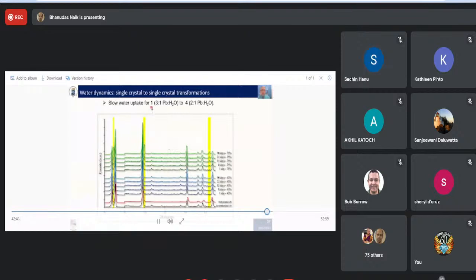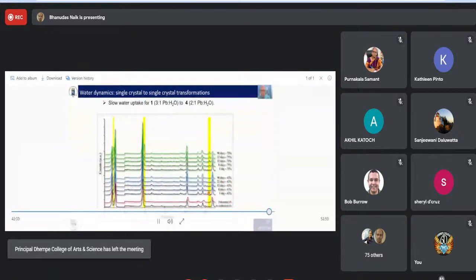And you also can have 1 to 4, but this is a really long time. You can see that if you have 1 as synthesized and 3 is dehydrated, and then if you leave it 1 day, 3 goes to 1 again. And then after 8 days, you can see that there's almost nothing happening at 43% humidity. It's all the same. But if you have 75% humidity, as some days are like here, you can see that the next peak is now growing in around 17 degrees. And you can see here as well, the next peak starts growing in here as well, and the middle here.